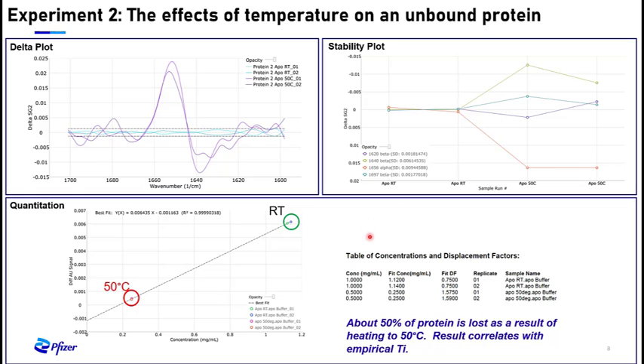By default, because of the software, we still get a calculated protein concentration for our samples. At the beginning, we said our room temperature sample was prepared at 1 mg per ml as determined by UV 280. Here, the calculated concentration is a bit higher at 1.1 mg per ml, but that's very close to our UV calculation. More interesting is the heated sample you see here. Our UV 280 determined the concentration for this sample to be 0.5 mg per ml. After heat treatment, the concentration is now only 0.25 mg per ml, according to the AQS3 software.